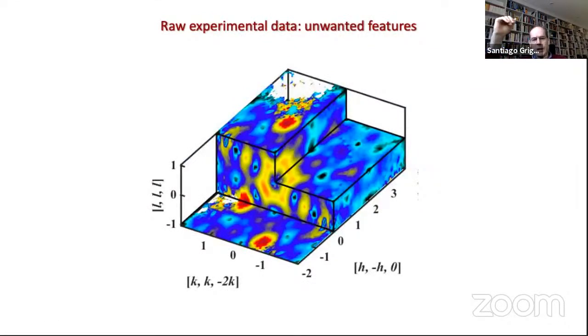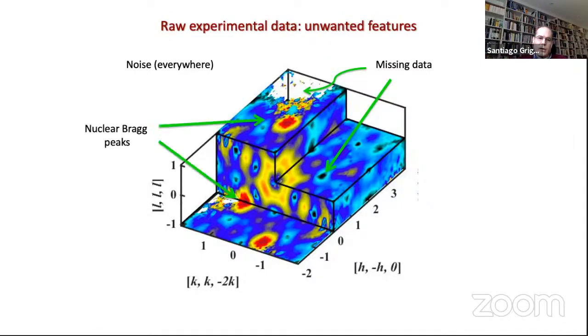So we took a critical view of our data. This is the raw experimental data. And you see that there are different issues here. One is, of course, with any other experiment, there's noise. There's noise everywhere. But you also see that there's some missing data. So these are bits where either you have some shadow from a can or something in your experiment, and also you have the nuclear Bragg peaks, of which you're not interested, right? So we're interested in the magnetic part, not in the nuclear part.